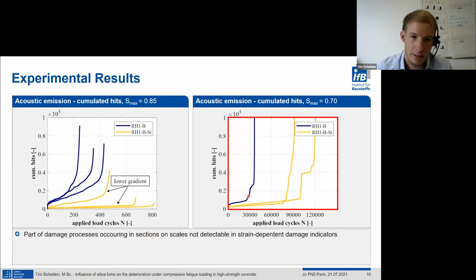Here we can see this stepwise curve as mentioned before. The stepwise curve is an indication for a part of the damage processes that occur in sections and on scales that are not directly detectable in the strain-dependent damage indicators, like the compressive strain. In the more horizontal parts, here, for example, or here, equilibrium states dominate in the microstructure so that fewer hits are detectable.